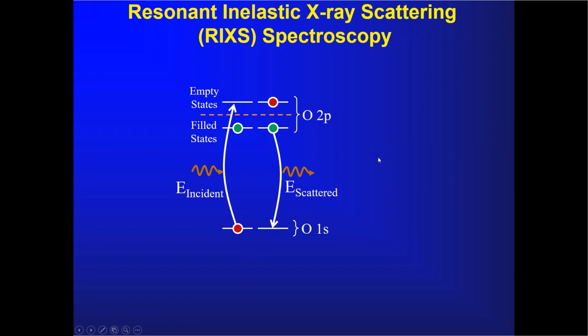And one of the techniques that we have found useful, and others too, is RIXS, resonant inelastic X-ray scattering. So just to remind you how this works, one ejects an electron from a core state to the empty states here, and then looks at the decay of electrons from the filled states just under here back to the core level. And if one does this for the oxygen 1s, the oxygen K edge absorption, then it's oxygen K-edge RIXS spectroscopy. And the oxygen RIXS is a very useful probe of the nature of the oxygen electronic states, especially mapping out the oxygen valence states, as we'll see.